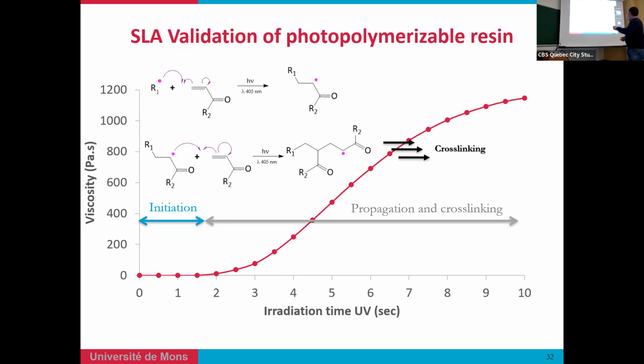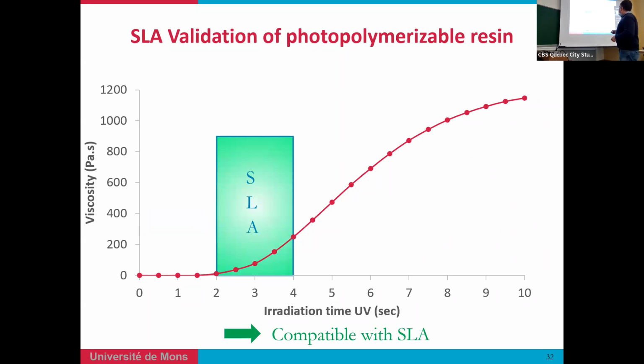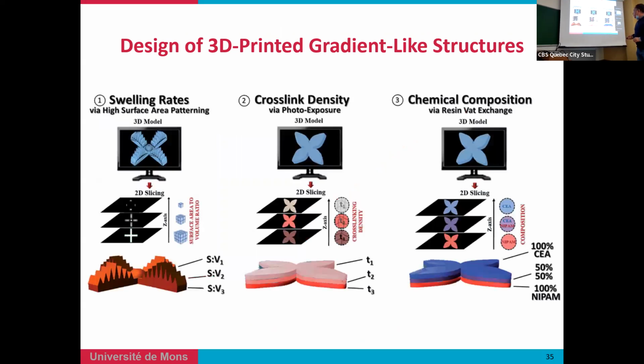This increase of viscosity is what you're looking at regarding 3D printing, particularly a window we call the stereolithography window, which is between 2 and 4 seconds. You can use a longer printing time, but sometimes you get issues related to the definition of your final object, so you need to make a compromise using this type of processing window.